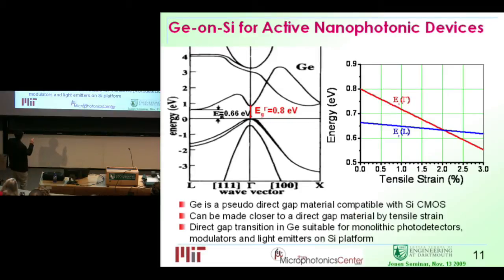So if you can utilize this one, we can do monolithic photodetectors and modulators. And if we do some further band engineering, we have a promise to do light emitters on silicon too from this direct gap transition. One of the tricks you can play is to apply tensile strain onto germanium. So you stretch the lattice. What happens there is that if you apply enough strain, then there's a crossover between this indirect gap and direct gap. So that means it effectively becomes a direct gap material because the minimum value is here.